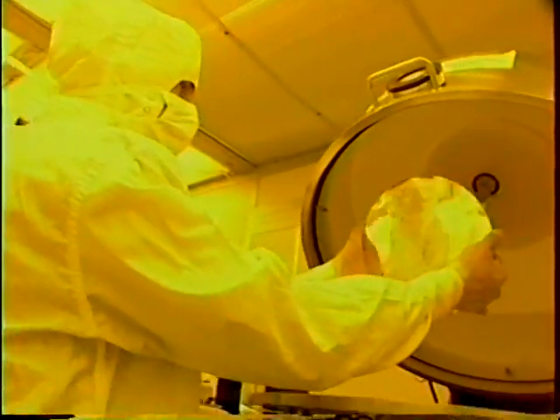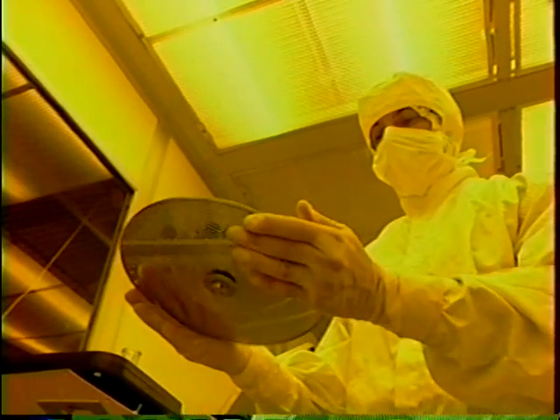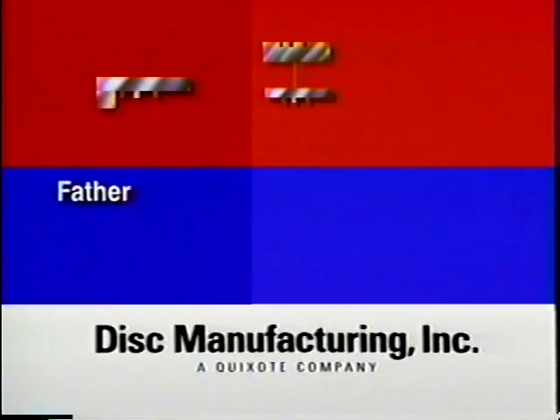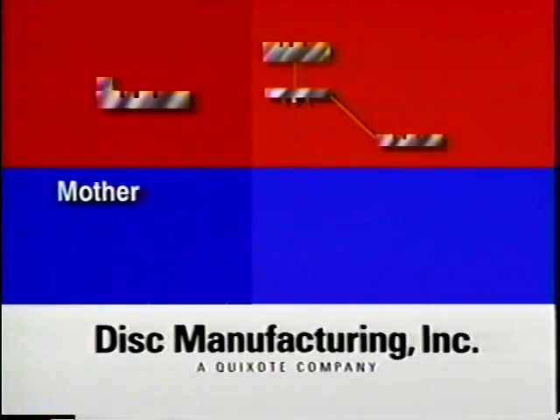Making a glass master is one thing, but producing thousands of copies of a CD requires a few more steps. The pits inscribed into the original glass disc must now be precisely transferred through a series of generations to a master mold from which the actual discs are formed. This master mold is called a stamper. To get to that stage, the glass disc is coated with a metallic layer. When this layer is separated from the glass disc, it contains an exact mirror image of the pits in the glass — everything that was a pit is now a hill. This is called the father. The father is then coated with a metallic layer; when that layer is separated, it yields what's called a mother — another disc that has the identical pattern of pits and lands as the original glass plate. This same process of coating and removal is repeated on the mother to make the metal stamper.